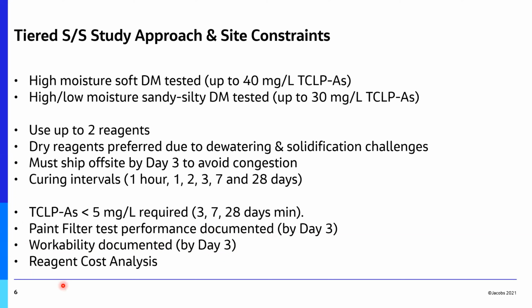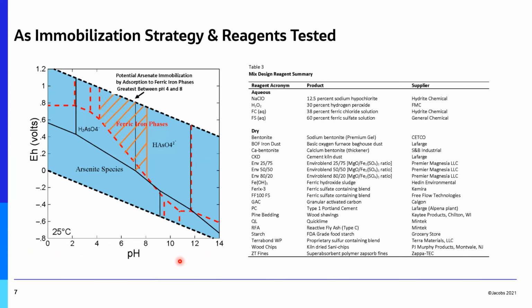And then the other thing that we had to do was track the dosing and the actual reagent unit costs with our dosing strategy. So the arsenic immobilization strategy, which was first and foremost, was that first we needed to understand what was happening in terms of the overall Eh, pH, stability of arsenic, right? Because we needed to ensure that it was going to remain immobile for the long period. And what we realized is that the leading strategies for arsenic immobilization actually have combinations with iron.